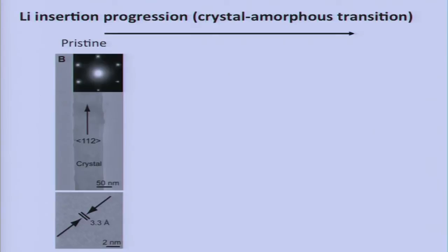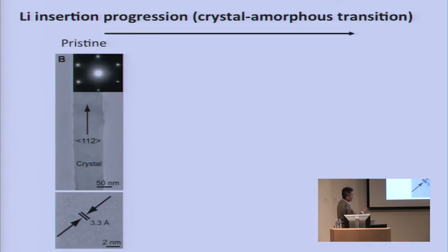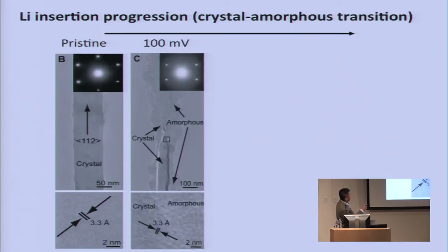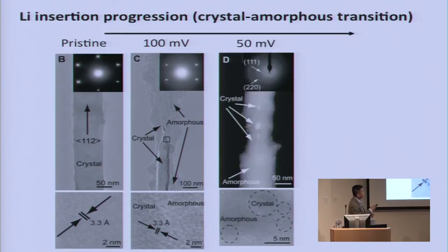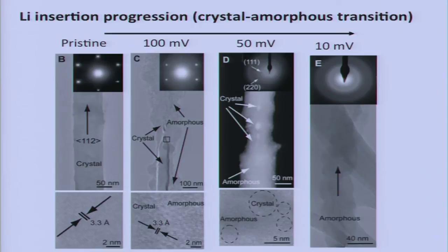But let's look at what's happening inside the materials. This is single-crystal silicon made by so-called vapor-liquid-solid growth, using tiny nanoparticles to catalyze the growth into nanowires. You put lithium in, and lithium cleaves the silicon-silicon bonding, forming lithium-silicon bonds, and it becomes amorphous. Silicon atoms move a very long distance in order to accommodate 4 times volume expansion. Eventually the whole thing breaks into an amorphous phase, but they're still connected. That was exciting when we saw this.